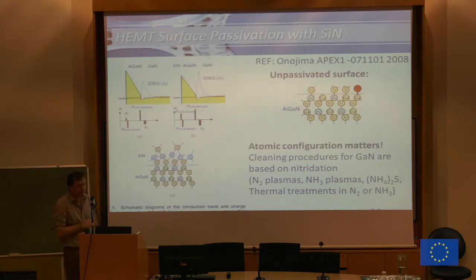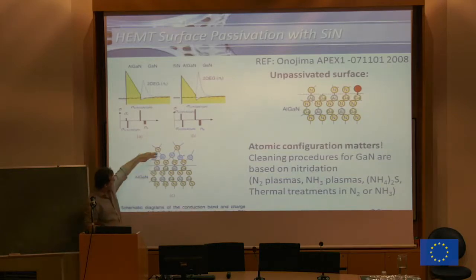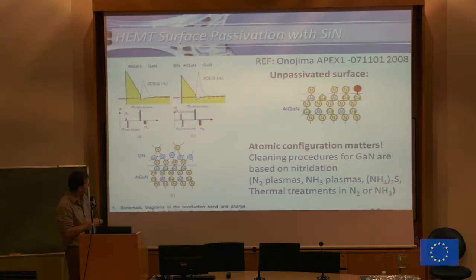And the reason why I have plotted this one here is because if you have a configuration where you terminate the surface with nitrogen and you then have the silicon atoms on top, in fact, now we have drawn the end of the crystal here at this level, you can in fact consider that the gallium nitride crystal is now extending till there, with the only difference that now you have replaced group 3 elements with a group 4 element. And of course a group 4 element on a group 3 place is really an element that will donate its electron. It's a kind of impurity doping in effect. But of course, in order to do that, you need to have this very perfect atomic configuration at your surface, which is why this topic has been studied for over 10 years in detail to get this particular thing right.